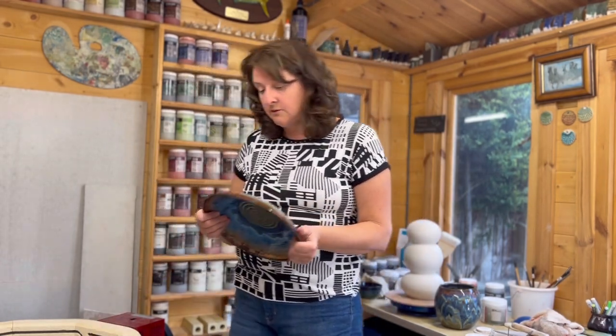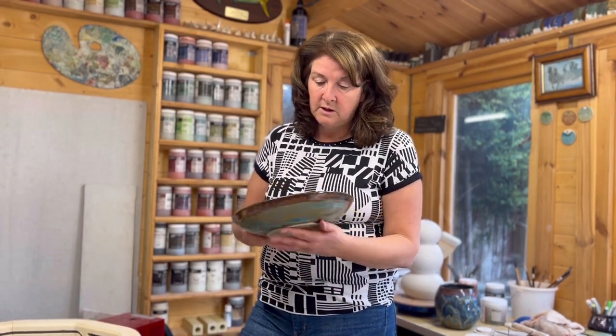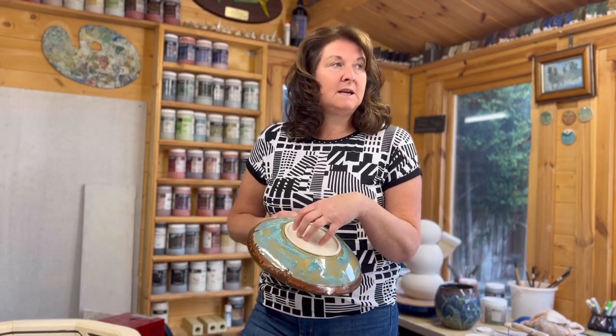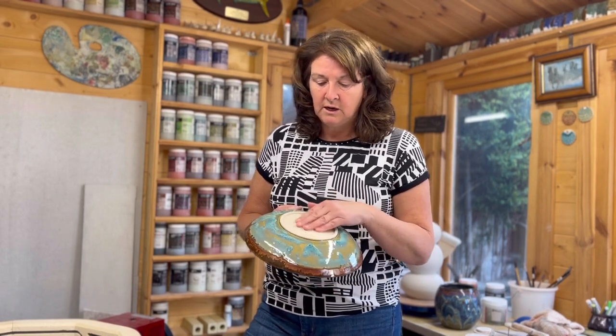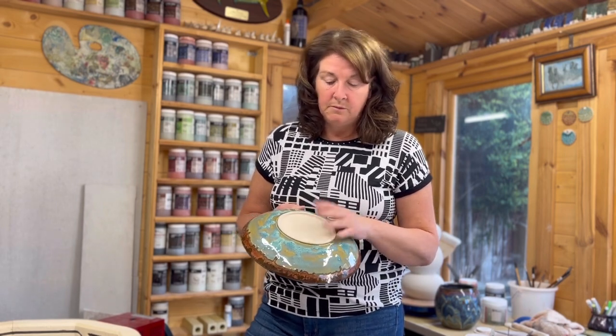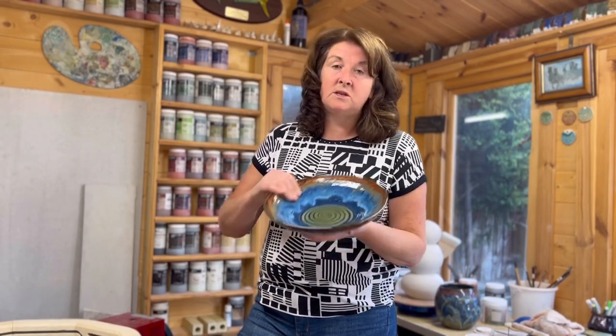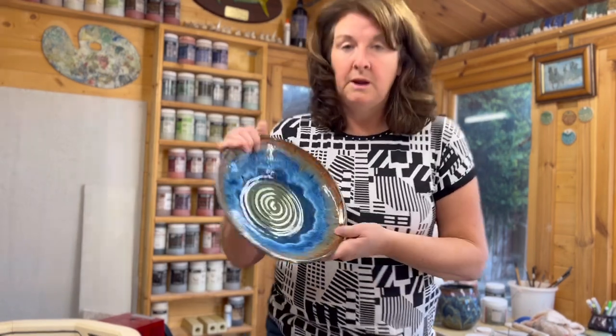onto the kiln shelf. Now, what I would say is this had been sitting for, I don't know, 4 months, 5 months or whatever, and it is made out of a different glaze, a different clay. I think this is made out of a slightly grogged clay that was one that I'd actually used for making products outside. But also with it sitting, whether it was dust, we've had this conversation, dust or whatever, I've got pinholes all over it.